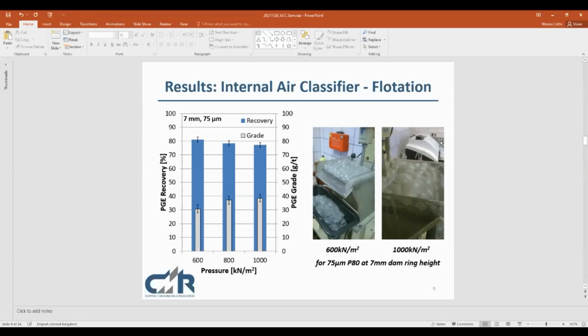This higher solid loading is linked to that increase in proportion of fines that we have when grinding at higher pressures and high dammering heights. So although we have a similar P80, we're generating more fines which are reporting to the froth and destabilizing it. One thing to note here is that we just used a standard flotation reagent suite that was typically used by Anglo Research for their ore flotation. Something that I suppose is another PhD right there is looking at the dry versus wet flotation recovery, and the need to optimize reagent suites for the vertical roller mill, if it's really going to get a true comparison. So expectations there are being overshadowed by froth phenomena linked to the increase in fines portion.